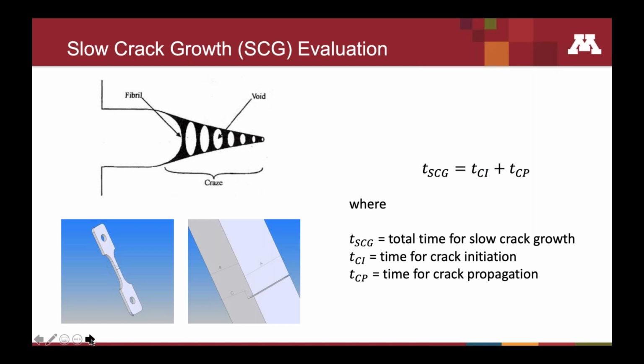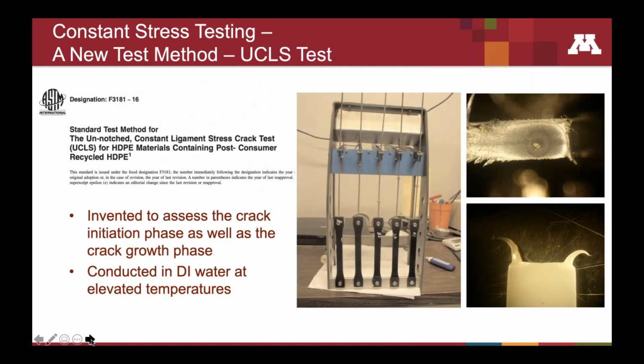With recycled materials, we had to think a little bit differently because if we would do this same notched test for recycled materials, we're really not going to understand or find the effects of contaminants on that stress cracking mechanism. And so what we ended up doing was inventing a new test. Rather than the traditional notched test, we came up with a new test which is similar in design, but it involves testing unnotched specimens. And the reason for that, again, is so that when a specimen does fail or does crack, we wanted that crack to be initiated by a contaminant so that we could really understand the effects of these contaminants on the service life of these materials.